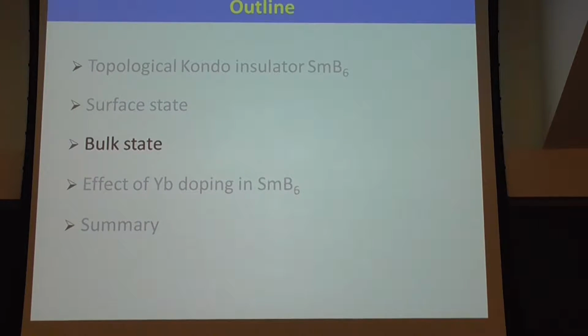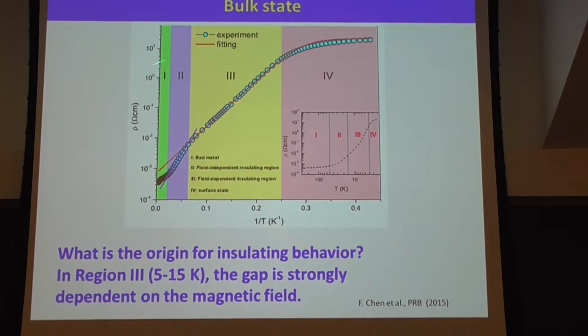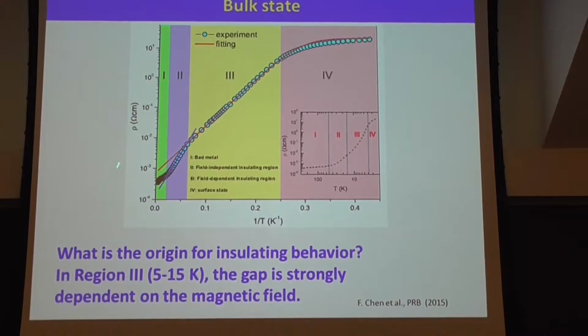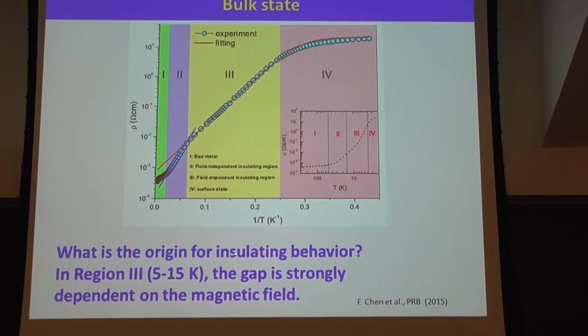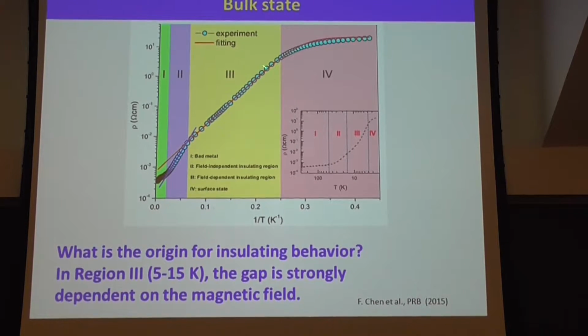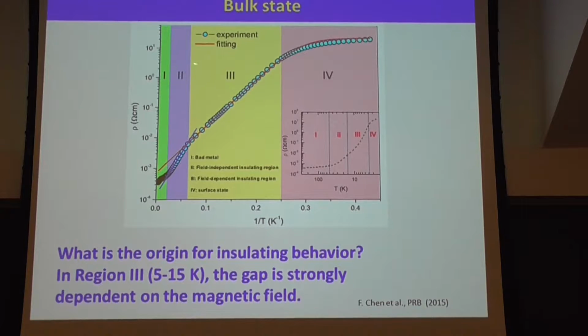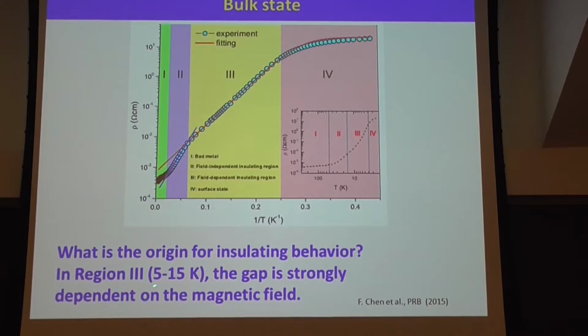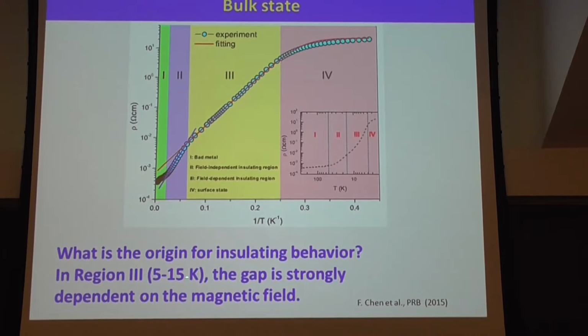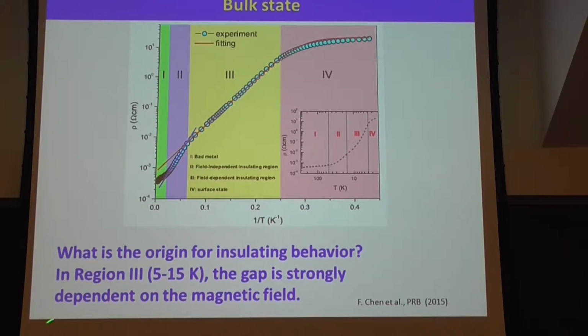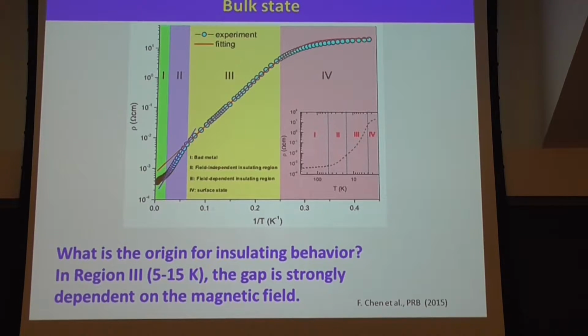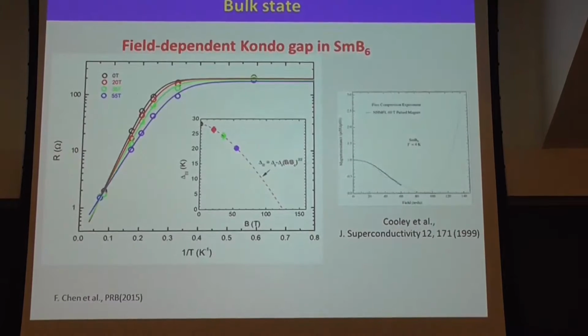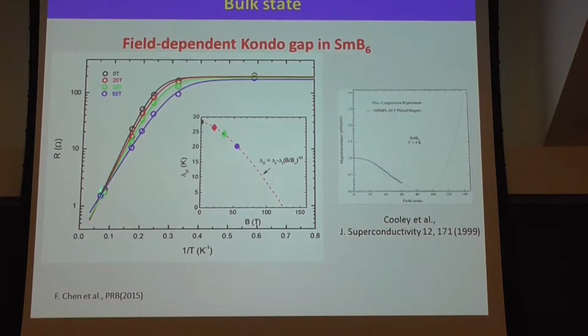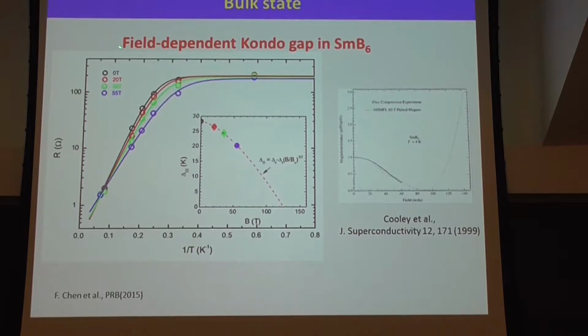Then for the bulk state, just before I talked about this, this is the resistivity as a function of 1/T. What is the origin for the insulating behavior? This region we call region 3. This is from 5 to 15 Kelvin. The gap is strongly dependent on the magnetic field. Later on I will show you that. Okay. Here is all the data for the resistivity as a function of 1/T.